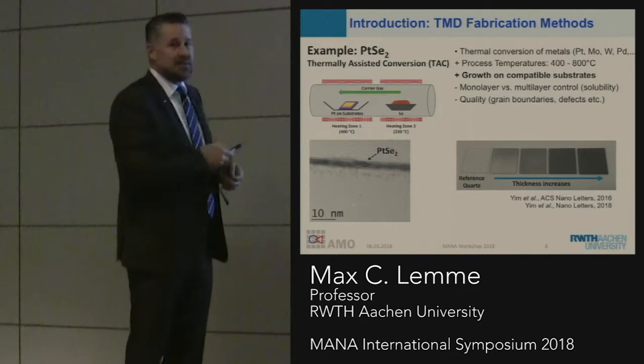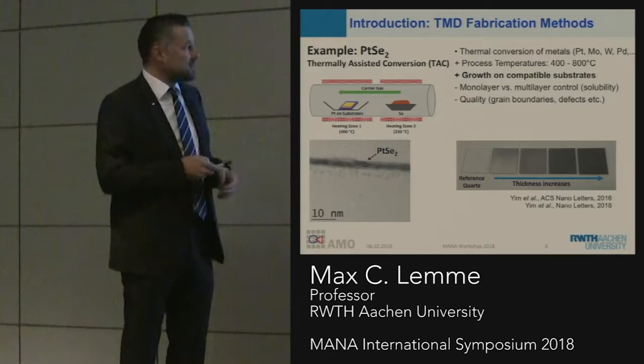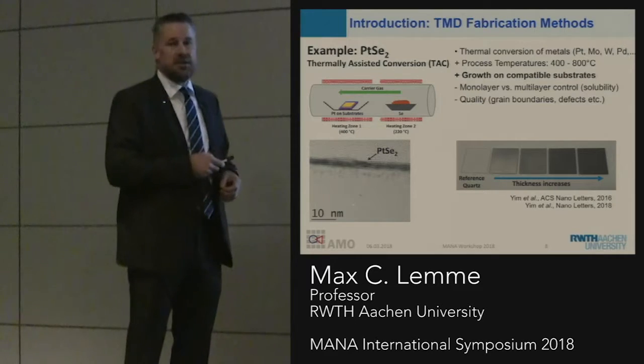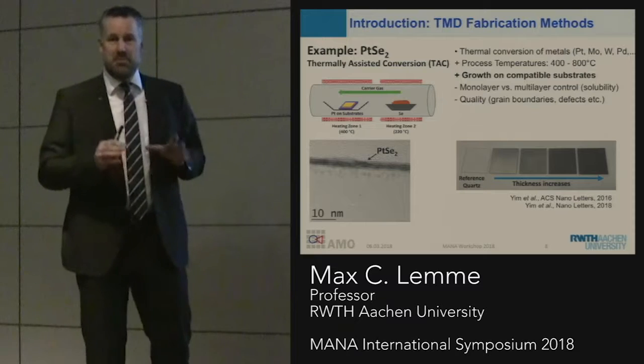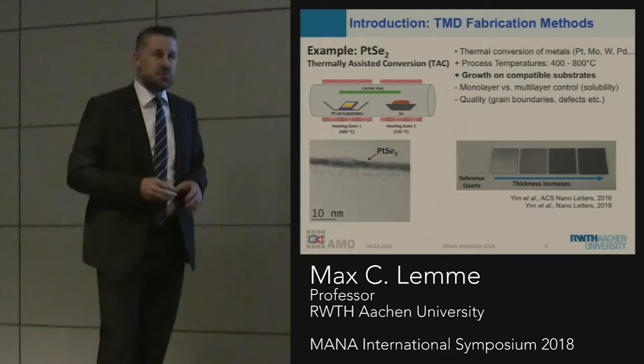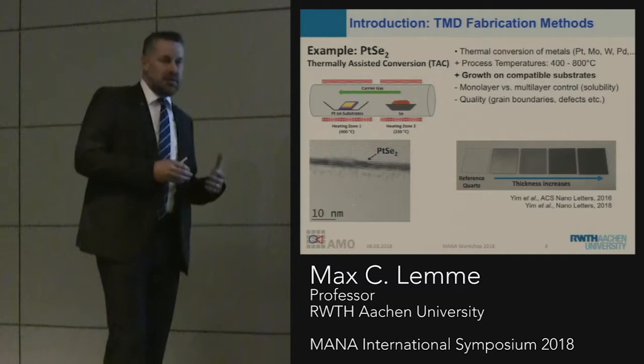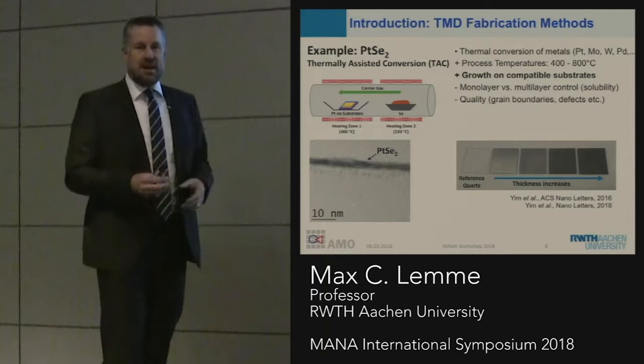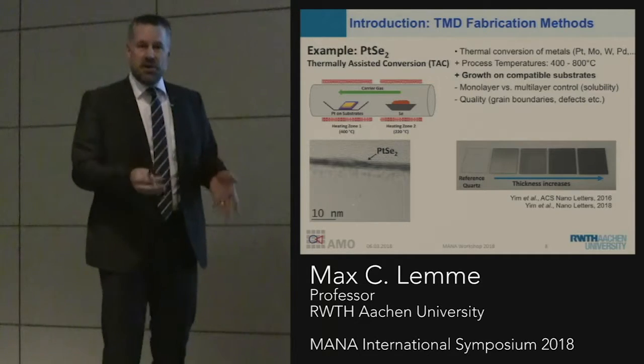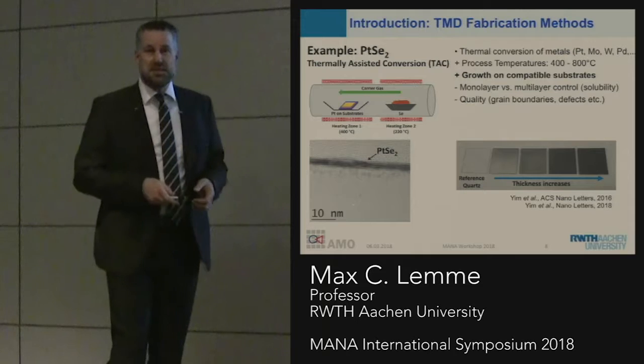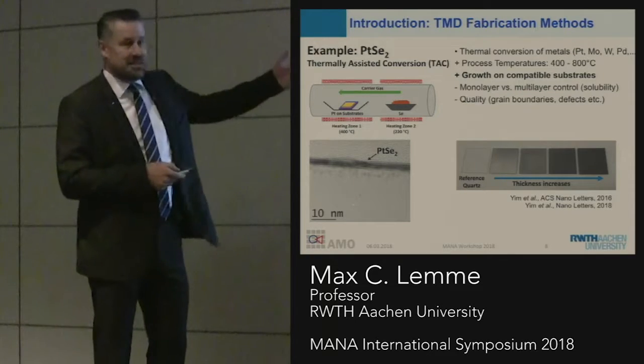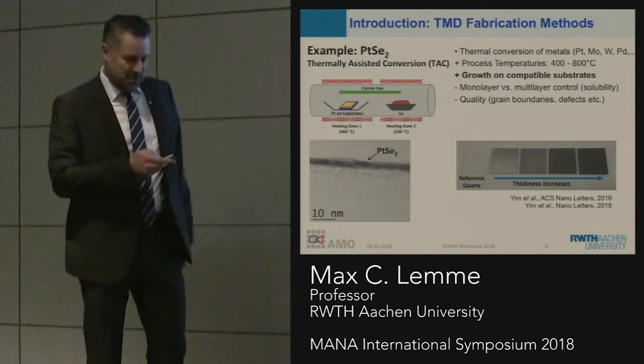The nice thing about this platinum diselenide, and that's why I chose it, is that it can be transformed at 400 degrees C. This makes it compatible with back-end of the line CMOS processing, and so it could in principle be integrated after making a CMOS circuit without destroying the functionality of the CMOS, and you would then add this functionality due to the 2D material.